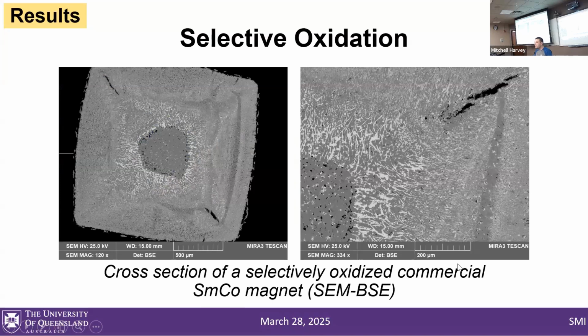We go to SEM now. This is a much higher resolution SEM image of a magnet, a commercial magnet that has been fully selectively oxidized. We can see a lot of interesting things. This is a backscattered electron image—the brighter the area of the image is, the higher the atomic number. So the very bright areas are rich in samarium, and the very dark areas are very samarium poor. Hence, bright areas are samarium oxides, dark areas are cobalt metal.